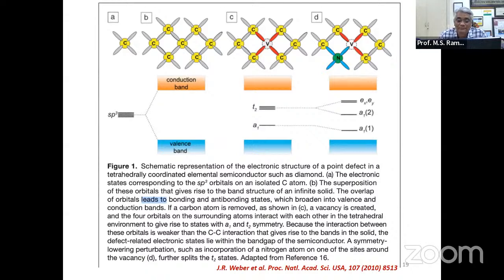But then the interesting thing is, along with nitrogen doping, if there's a neighboring vacancy, if the neighboring vacancy pairs up with the nitrogen that replaces the carbon, you'll have this NV center. That's a fundamental building block to realize room temperature qubits, right?